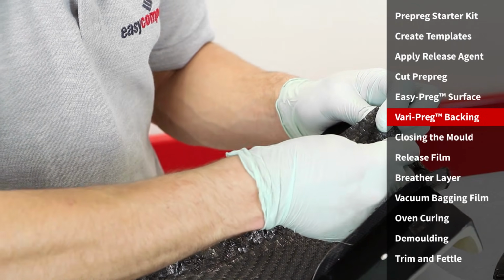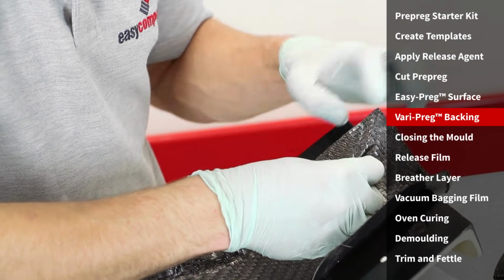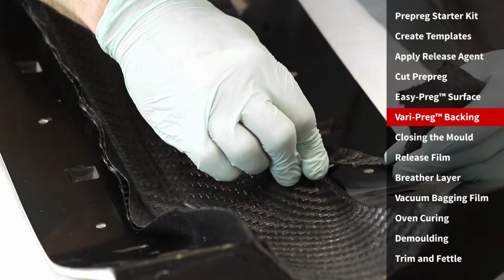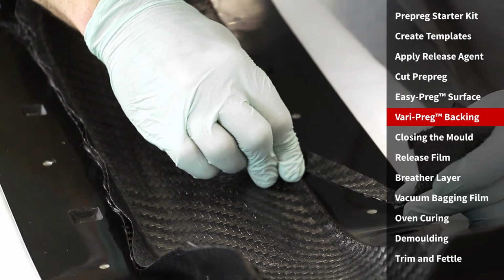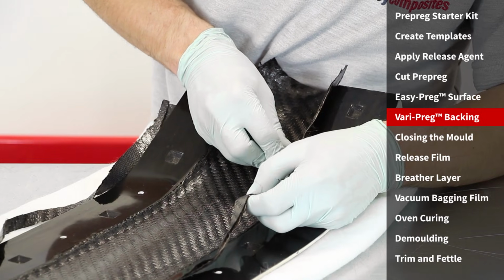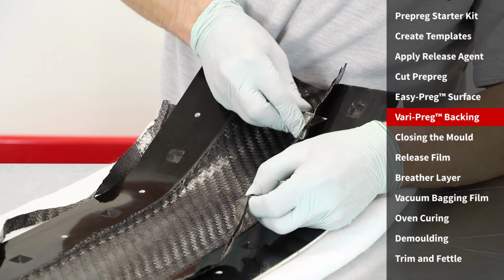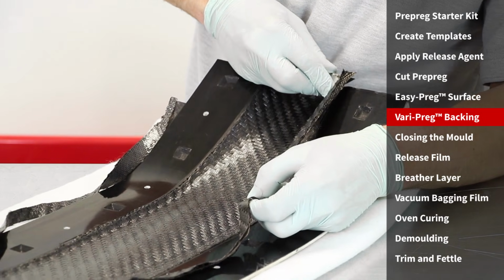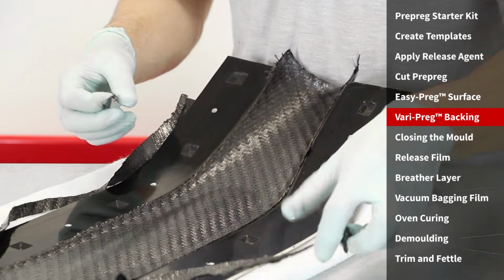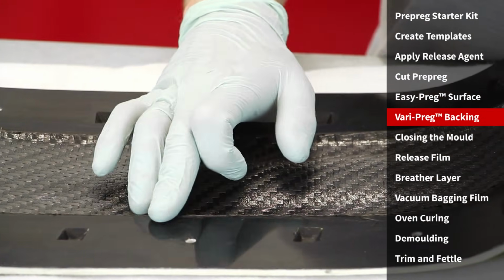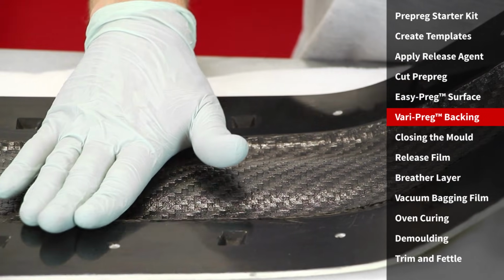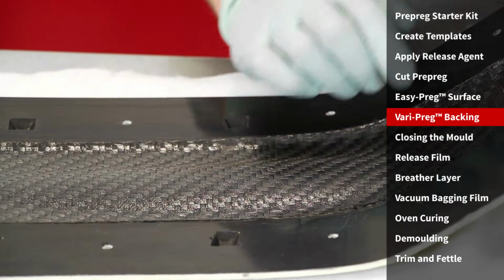With the 2 plies properly laminated into the mould, the excess is trimmed off with a sharp knife blade. Ensure that the blade is kept flat and does not scratch and damage the mould flange. You should make sure that the cut line is neat and level with the flange. This will ensure a neat join in the part is provided.